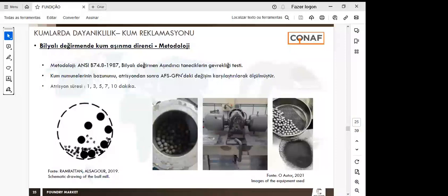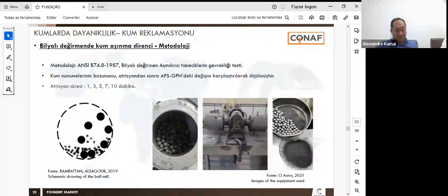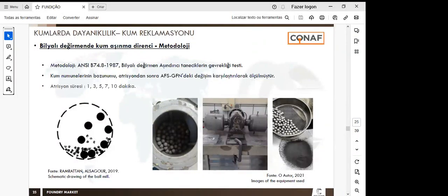We measured the sand attrition resistance with a ball mill according to the ANSI procedures. The test consists of a cylinder that rotates with steel balls together with the sand sample. Everything is controlled and standardized. The breakdown of the sand samples was measured by comparing the change in GFN after the attrition. We did this study at different attrition times, in 1, 3, 5, 7, and 10 minutes.